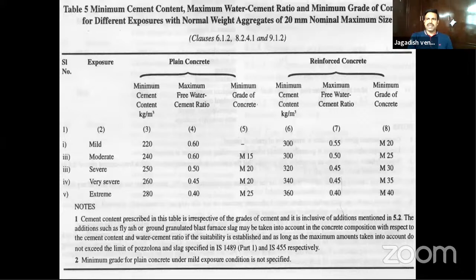So this is a famous table in IS 456. We design the concrete mix based on the exposure condition, very, very important. There are 5 exposure conditions that are defined: mild, moderate, severe, very severe, and extreme. The minimum grade of concrete for RCC is M20, and M40 is for extreme. And then the maximum water cement ratio allowed in the concrete is 0.55, and the minimum cement content per cubic meter of concrete is around 300 kgs.